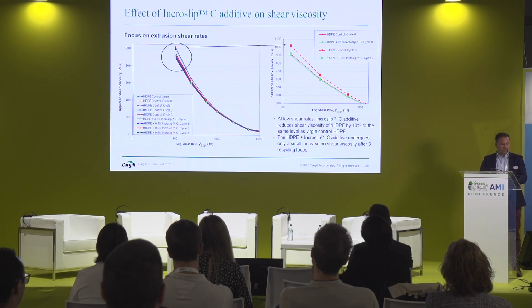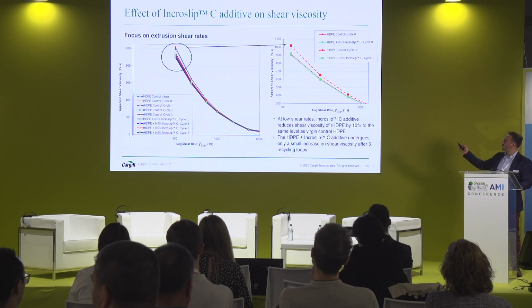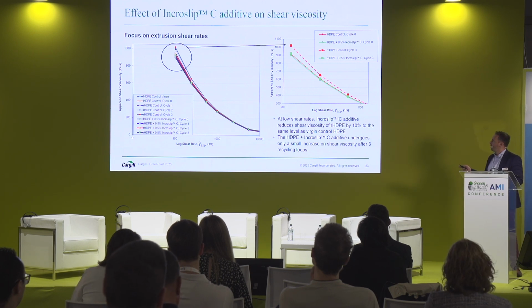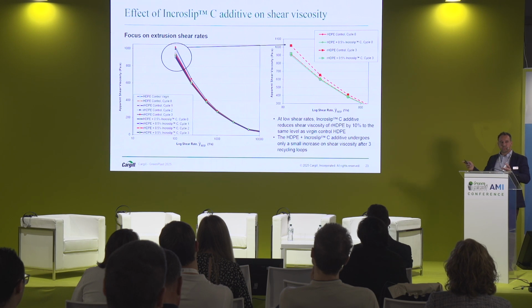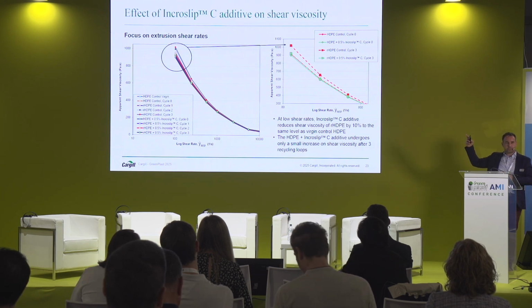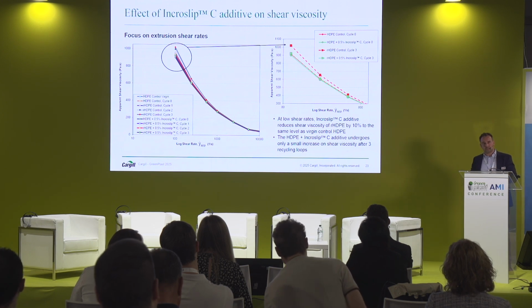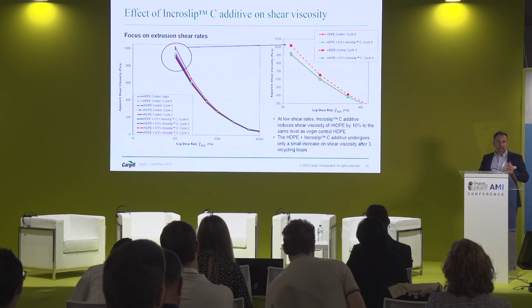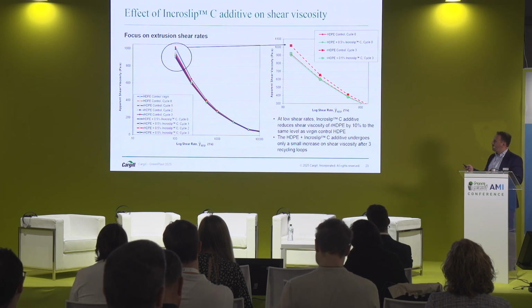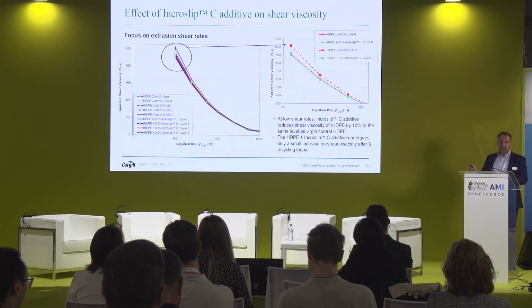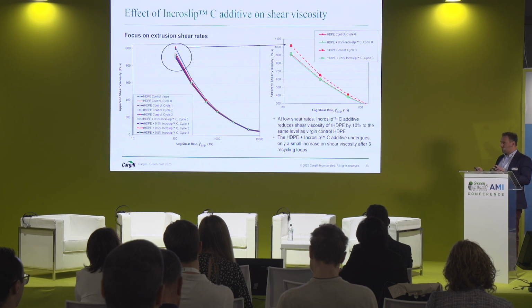And we repeated all these 3 cycles again. What we found, if you focus on the right-hand side, the red line is blank, virgin HDPE at the first conversion cycle. After 3 recycling loops, the shear viscosity goes up, which means the polymer is getting degraded, and there is cross-linking, which restricts the flow. With the additive, you can see that after 3 cycles, there is barely any change, which means the additive allows HDPE to retain the original properties much better.